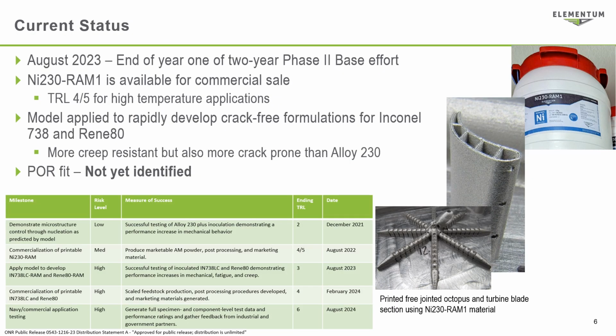We are currently in the second year of a Phase 2 base effort, and the Nickel 230 RAM1 has already been approved for initial commercial release at a TRL level of about 4 to 5. We've also started to apply the modeling approach to gamma prime containing nickel superalloys. These are some of the best nickel superalloys in terms of high temperature strength and resistance to creep. Creep is the resistance to deformation over long periods of time and high stresses at temperature. These alloys are used to make turbine blades because of these properties.